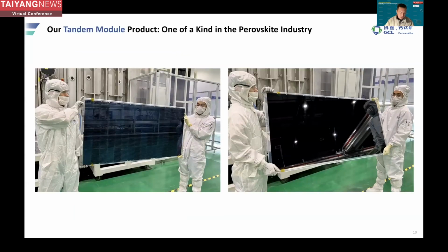And what I want to emphasize here, what's the most important achievement recently, is the tandem module. We always believed that we should first finish our research on the mono-junction module before we can really go to tandem. And now, since we have already reached 18% efficiency, we believe that we are good enough in the single junction module. So we are now able to construct a tandem module of this size. When we say good enough, it doesn't mean we will stop here. The efficiency for a single junction perovskite module will still grow. It will grow to 20, 21, 24, and I think we will not stop before 26% efficiency. But now we are able to construct a tandem module, which is already better than any kind of single junction silicon module.